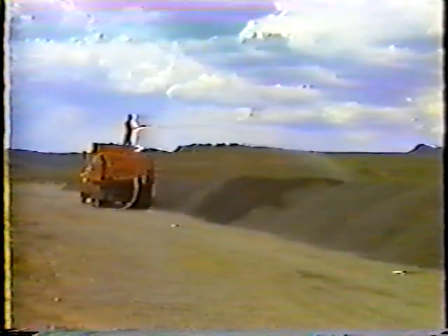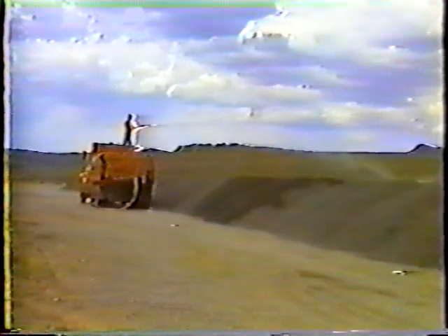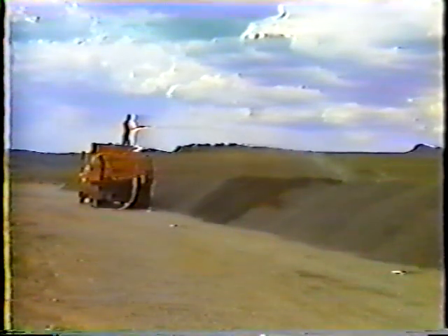Two of the most important things about the cover material are that it be clean and damp. Here's why. The liquid asphalt has to bond not only with the pavement, but also with the cover material. And if there's dirt or dust on the cover material, it won't stick. So the cover material should be hosed down a day or so before seal coating. That way it's not dripping wet, just damp. Be careful not to water the chips too much. Excess water will create mud at the bottom of the stockpile and contaminate the cover material. The best way to avoid contamination is to place the stockpile on a hard surface.